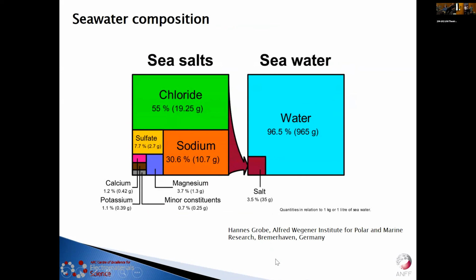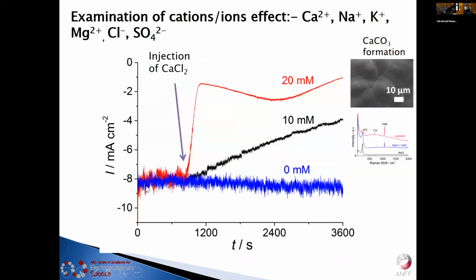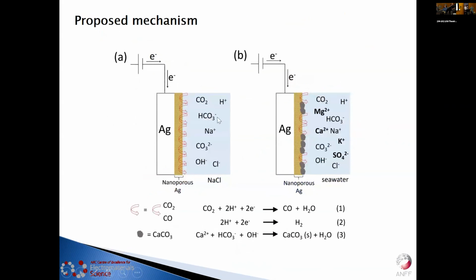You can see here there's not only sodium or chloride, we have many other cations and ions. So what we did was add the cations and anions we have in the lab into the electrolyte, and we found that if we inject calcium chloride, then you can see the drop in the current. At 10 millimolar it's quite significant, and at 20 millimolar even more. And this was confirmed to be calcium carbonate formation. So that means if there are cations and anions which are not inert with the CO2, there's potential for reactions.